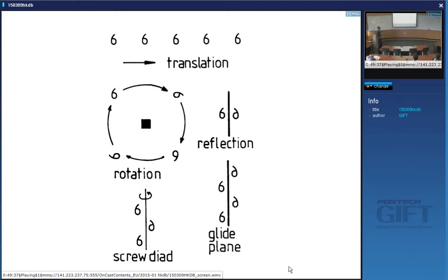Yeah? There is another kind of plane which is called a glide plane. So, if I take this and I reflect it along here and then translate it by a fraction of a lattice parameter, say half a lattice parameter, then I recover this object here. There's nothing left here. So this is a reflection plus a translation by a fraction of the lattice parameter. That's called a glide plane. Now, when you look at the macroscopic shape, this appears like a mirror plane, simply because you can't pick up that half a cell edge translation. Okay? But when you look at the details of the structure, you find the glide plane. Okay? But you need resolution on the atomic level.